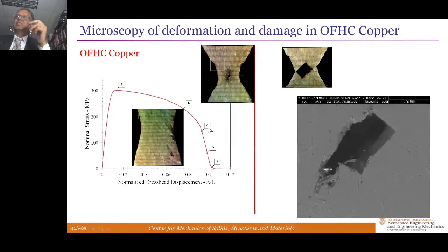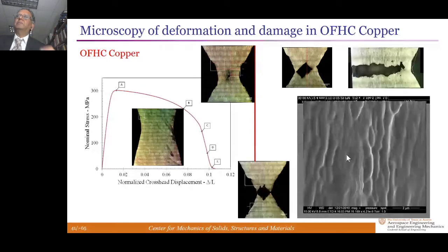And we've been able to assemble this alternating slip mechanism to argue that that is what can create this rectangular cavity inside a polycrystalline copper specimen, but it has to be pure. If it has second phase particles or other impurities, it will destroy this mechanism completely. I'll talk about simulation of this in a few minutes, and also about additional measurements.